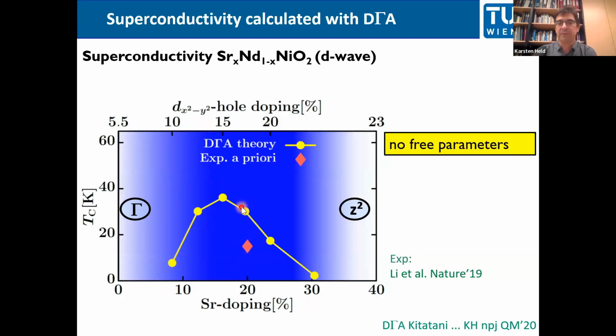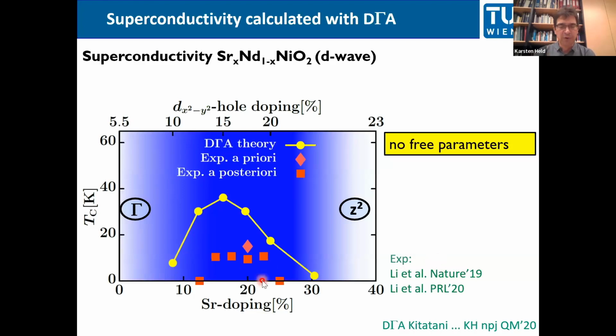If we would have used a larger U value, we would have been on top of experiment, but we thought that is way too much, too large a U parameter that shouldn't be realistic anymore. When later experiments came out, and that was the first experiment, and given that we really calculate TC without adjusting parameters, the agreement already here was very satisfying to us. But of course, there was a factor of 3 or whatever disagreement between experiment and theory. There was also this little dip in experiment.